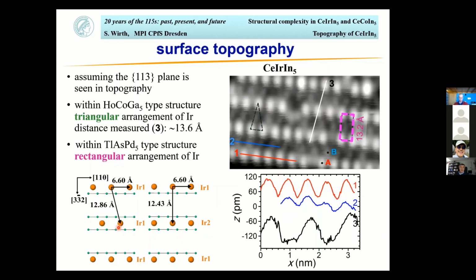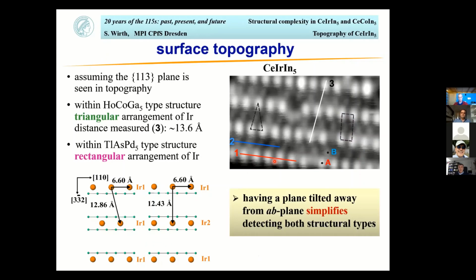But if you have the other type of structure, then due to this displacement of the iridiums by this half-half in the 0, 1/2 plane, we now expect to see a rectangular arrangement, and that's exactly what we are seeing here. And also, if you now look at the distances, that fits well. I mean, not too well, but please keep in mind, we have a steep inclination here, so we have to correct for that, and the error bar in this case is much higher than if we go along the lines without any inclination. And I think it's actually pretty nice to have a tilted plane, a plane tilted away from the AB plane, because it can then much more easily detect such different structure types.